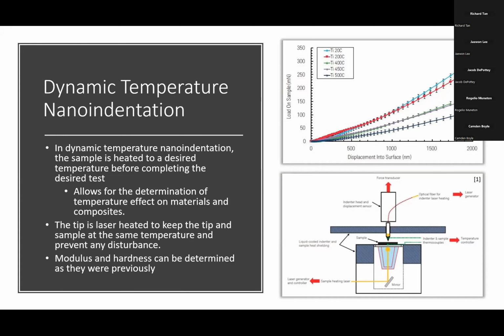If you look here to the right, you can see there's a diagram. The lower right image is a diagram of how you might heat up your sample and your tip. So you have a laser that is hitting a mirror at a 45-degree angle to reflect onto the sample to heat it up, with an optical fiber in the tip to heat it up to an equal temperature.